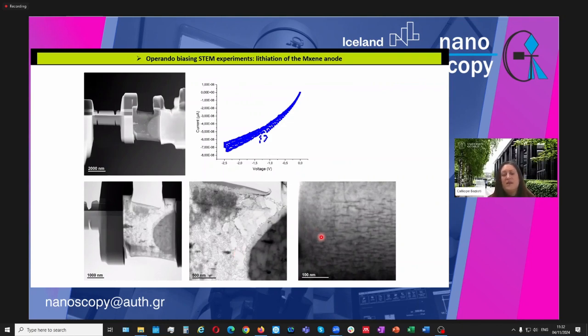And of course, on the MXene side, we had many stacking faults. Also threading dislocations that seem to nucleate from some of the stacking faults. So far the material gives the impression that we have an increase of the defect density after the lithiation process, but we are working on that.